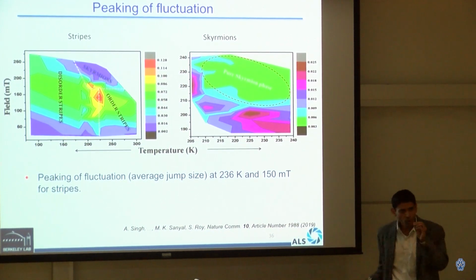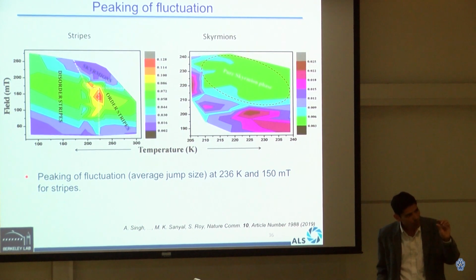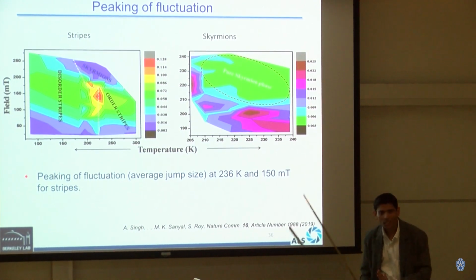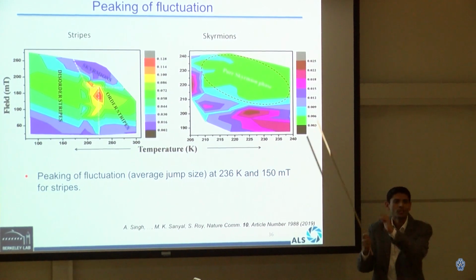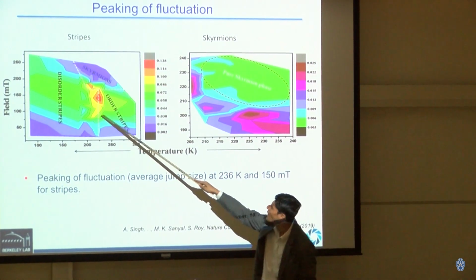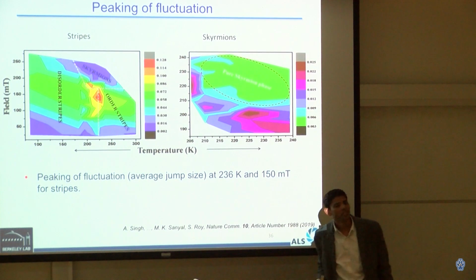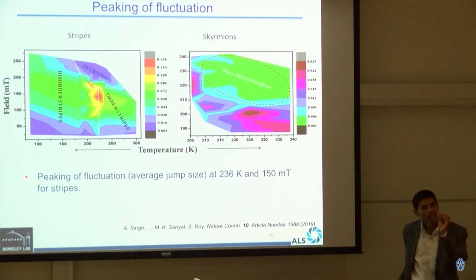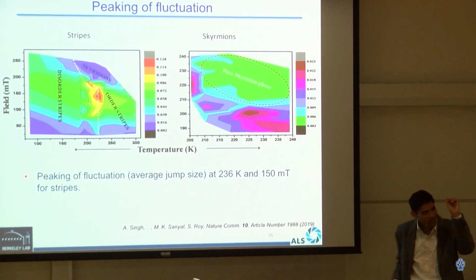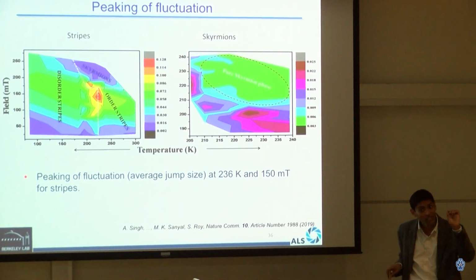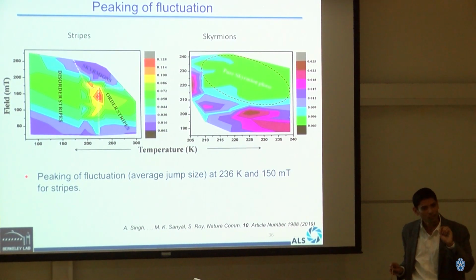So that means if we plot the size of the fluctuation, which is analogous to the size of the bubble and their appearance, they should peak as we are approaching the phase transition. So that's what we plot here, and we show indeed that's what is happening. It is really peaking up near the so-called critical point, right? So it is indeed a critical point, and this is important in physics for StatMech.